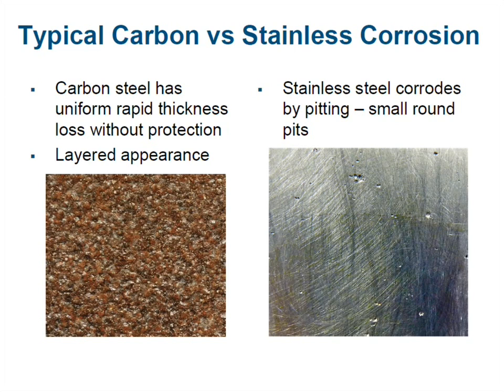Steve showed some pictures of the inside of the arch and the carbon steel with very little corrosion on it. As carbon steel corrodes, you get a layered appearance, and those layers actually tend to retain more moisture and accelerate corrosion. Stainless steel, when it corrodes, pits. So it's a very different corrosion process.